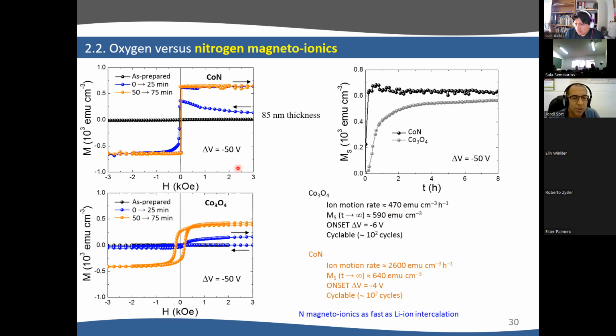Now, what happens if we compare cobalt oxide and cobalt nitride for a given condition, the same thickness of the layers and so on, and we apply the same voltage? You can see here that cobalt oxide is what I've shown before, this loop that increases with time while we are measuring. And here is the same for cobalt nitride, but the difference is that for cobalt nitride, after measuring the first loop, 25 minutes, we already reach a saturation magnetization that doesn't change upon consecutive loops. So between 50 and 75 would be the third hysteresis loop, and you can see the magnetization did not change. So everything happens for cobalt nitride in 25 minutes, whereas for cobalt oxide, it takes more than 50 minutes to still see a change. Actually, if you see here the dependence of MS with time, for cobalt nitride it is indeed very fast and it saturates. And for cobalt oxide, it takes a lot of time, several hours, to reach this steady state.